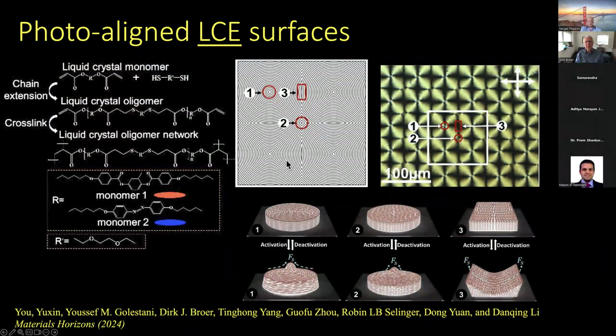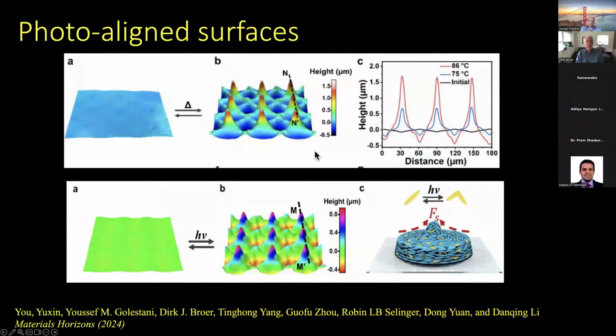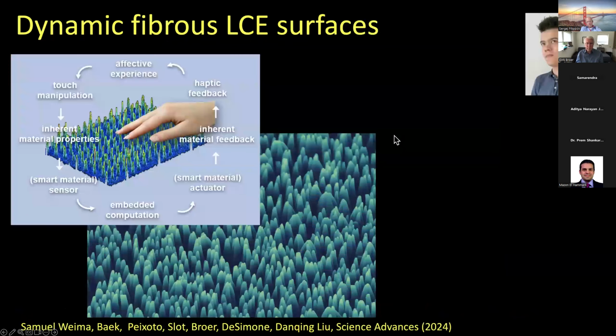So if you make a film which is initially flat, if you start actuating them, and that can be done by temperature or by light, you can go from an initial flat state to a corrugated state like this. And special here is that the corrugation is now even much higher than we could get with the pure liquid crystal networks by themselves.